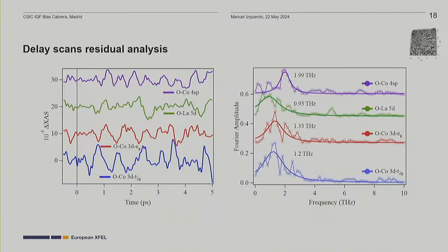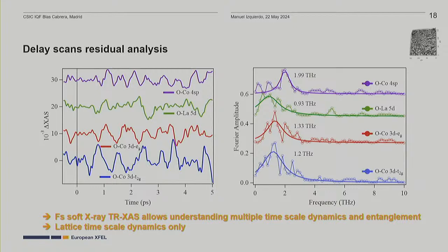So you can do an analysis of this by doing Fourier transformation, and then we have found that the main excitation, depending on the resonant energy you're looking at, can go between 1.33 terahertz and 1.99. This data is still under analysis, because in principle what we know is that this 1.99 terahertz can be assigned to a phonon mode, but for the other, in principle, there are no phonon modes that can be responsible for these oscillations. So the conclusion is that soft X-rays allow understanding multiple time scale dynamics and also the entanglement between the different degrees of freedom of the system.